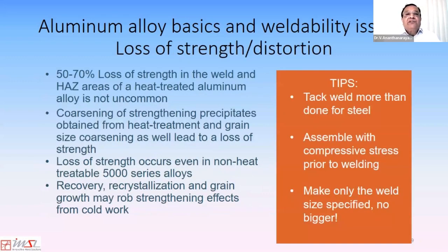And other issues with aluminum alloy weldability are 50 to 70% loss of strength in the weld and heat affected zone areas. And if you weld a 6000 series alloy like 6061 T6, a 50 to 70% loss of strength in the heat affected zone is not uncommon. And this is why the aluminum alloy structures have not gained widespread use in structural applications that involve cyclic loading and other heavy stressed mechanical loading applications.